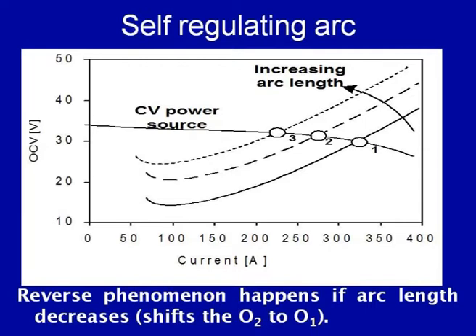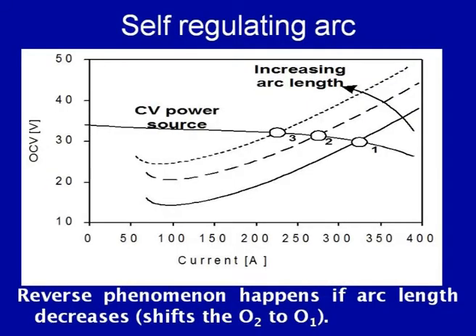We can see the reverse example also. Say, for example, a decrease in arc length takes place. The decrease in arc length due to any reason will lead to a change in arc characteristic, say from operating point 3 to operating point 2. So, this change in arc length will shift the operating point due to the change in arc characteristic, and this will be accompanied by a decrease in arc voltage. And we know that with the constant voltage type of power sources, a reduction in arc voltage is associated with an increase in welding current, and this increase in welding current is very significant, which in turn will help to increase the melting rate.